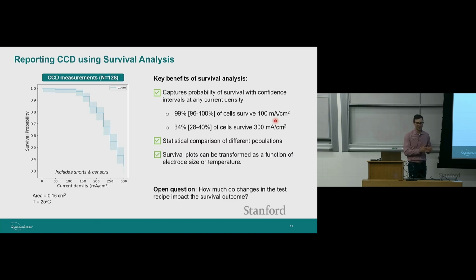What's reported in literature, if you look at other people performing similar tests, is they'll report typically one data point of around 1 milliamp per square centimeter. The highest that I've seen reported is 13. I have some questions about whether that's a real result, but putting that to the side, the range of 1 to 10 is typically the best in the world that you'll find published. And what we're showing here in this result was 99% survival to 100, about a third surviving to 300 milliamps per square centimeter. So the main takeaway, though, is that survival analysis is the main technique that we use for quantifying our results.